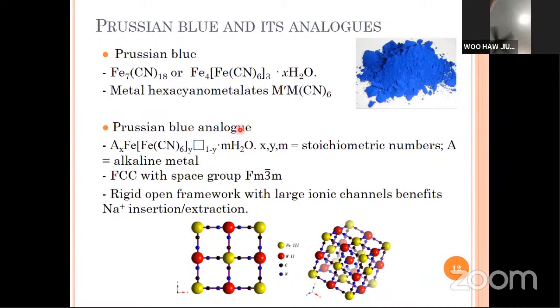Now, based on literature review, different groups of researchers are trying to synthesize a less defective crystal of Prussian blue analog with this empty box value, 1 minus y, as low as possible, because their observation is that whenever there is a high vacancy or a high defect, the interstitial water will basically fill up the vacancy, and that blocks the insertion and desertion of the sodium ion.